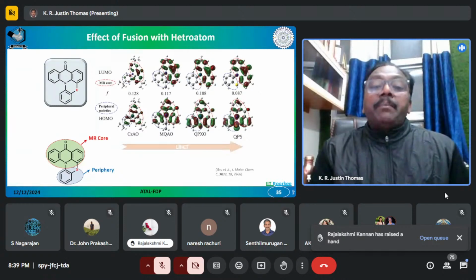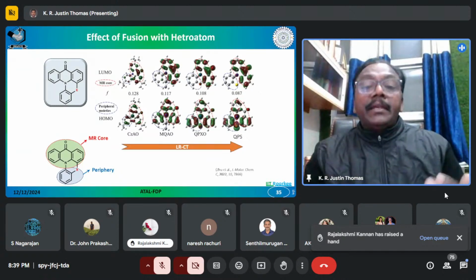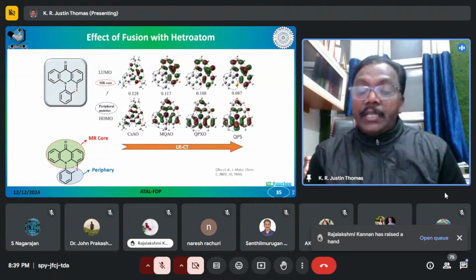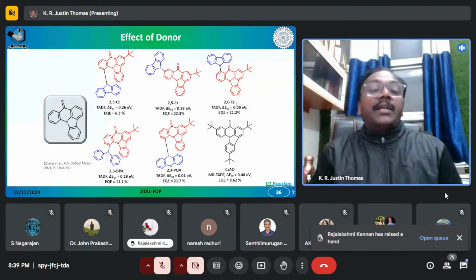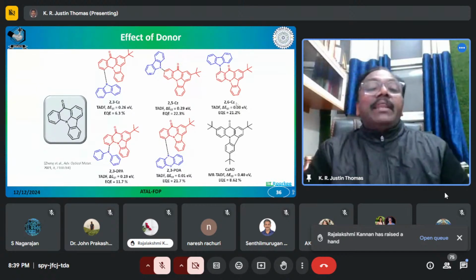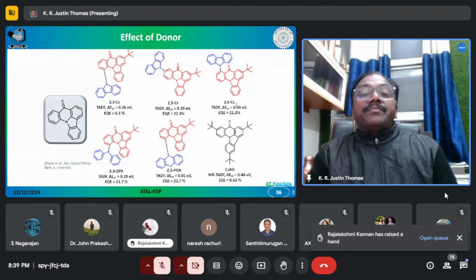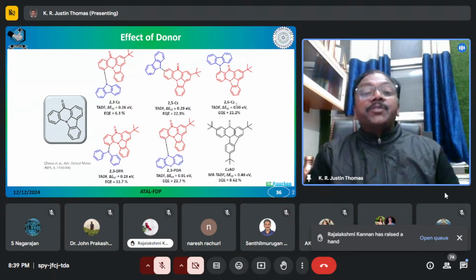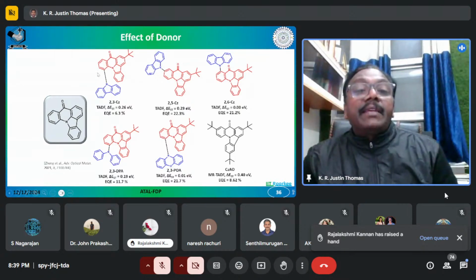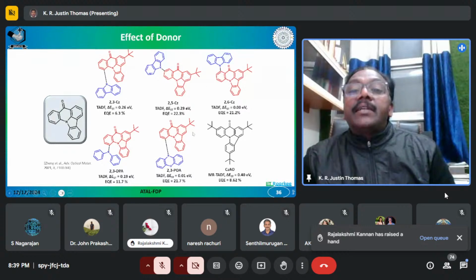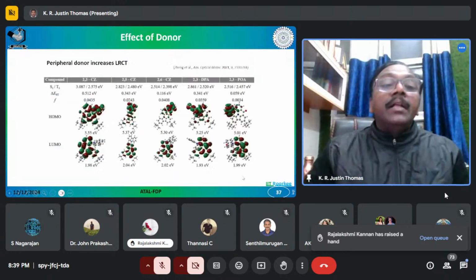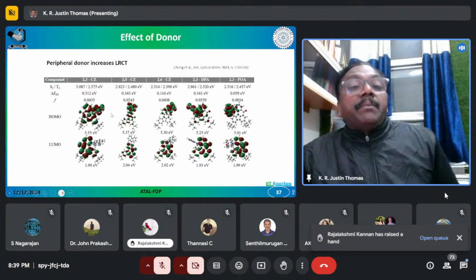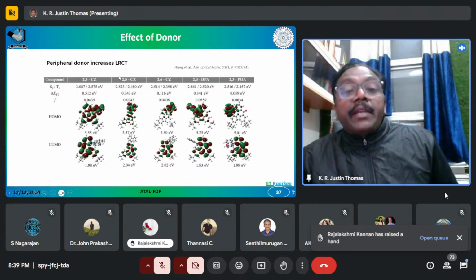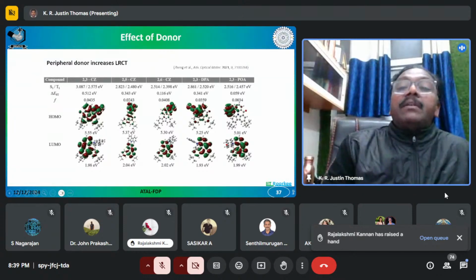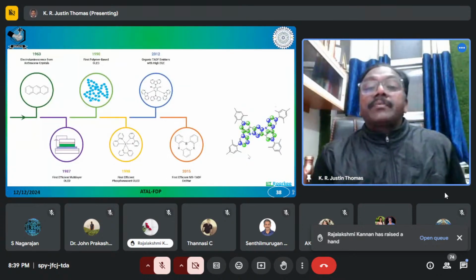So now what will happen when you increase the donor strength at the periphery? That is what you have seen here. So now you put a donor on the periphery, what will happen? It will increase the long range charge transfer. So that means that it will reduce the delta EST. That is what you are seeing here. When you put a donor group, the delta EST is decreasing. Okay, so this can also be seen by looking at this molecule. Long range charge transfer increases as the peripheral donor strength increases, or the donor strength at the peripheral group increases.